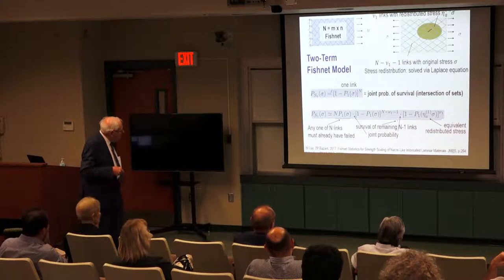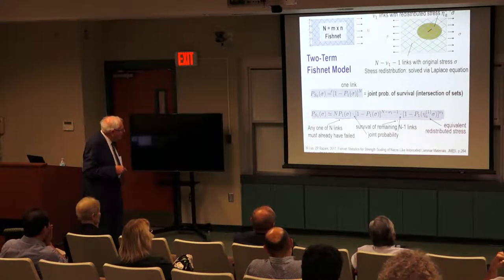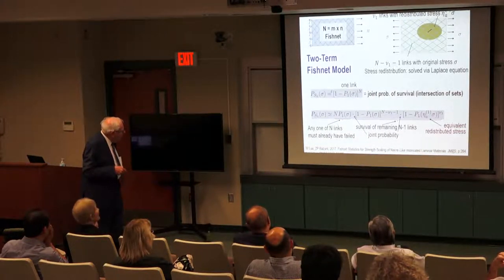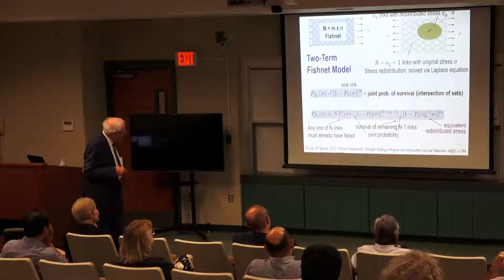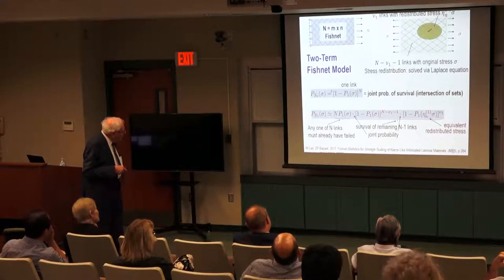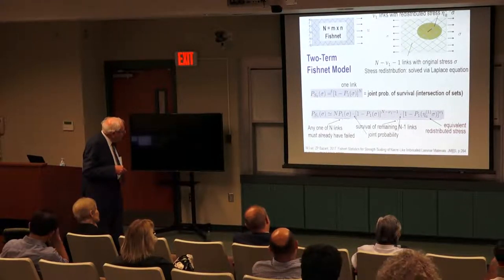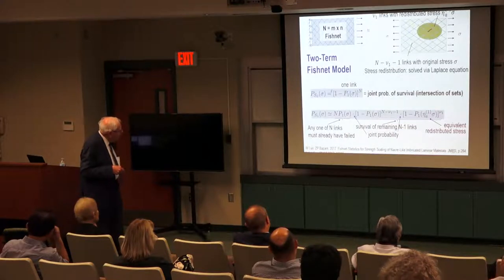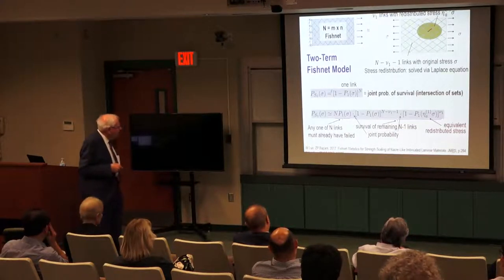One link fails, zero link before. That's Weibull distribution, weakest link model. Survival occurs if all links survive. This is probability of failure of one link, and this is probability of survival. And if there's n of them, the joint probability gives a product.